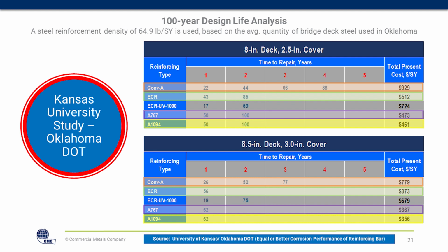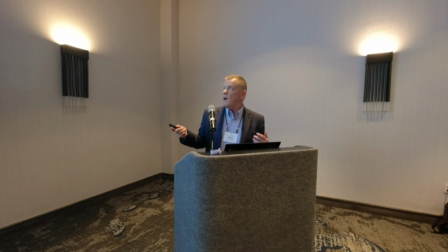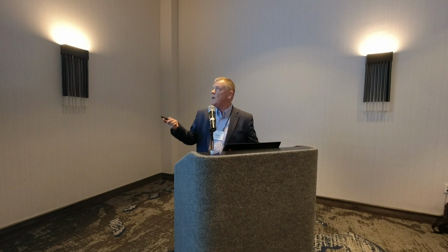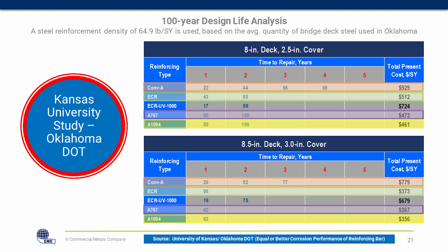This is a 100-year design life analysis. This is an excerpt from the University of Kansas study that was conducted by Dr. David Darwin, and it was released in 2021. But the key thing that we found here was he was looking at the average cost of bridge deck materials. This was funded by Oklahoma DOT. And so you have conventional up here on an 8-inch deck, and so you have 2.5-inch cover, and then this is an 8.5-inch deck with a 3-inch cover.